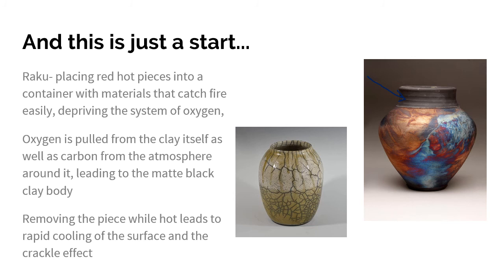And because you're taking raku from a red hot kiln and putting it into another container, that is going to make the exterior cool very quickly. And so when we talk about that crazing and crackling, that is an intentional effect of a lot of the raku glazes. So that's how we can get that crackle effect. So raku, very lovely technique. It's very versatile depending on the type of glaze you're using. You can do so many things with it. You can get that really shiny metallic copper color depending on the conditions and the type of glaze you put on.